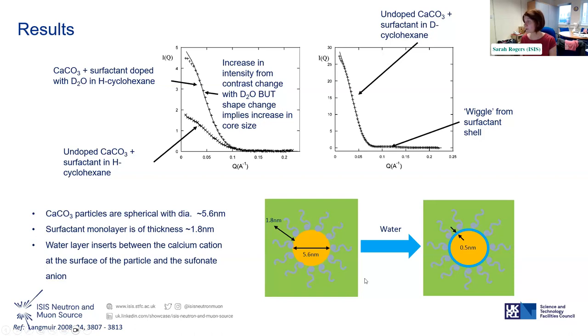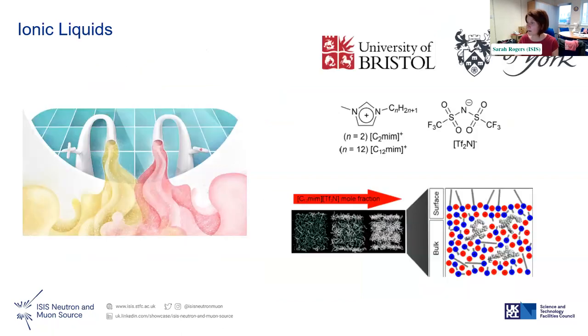And then when we added the water, it does indeed form this very thin layer in between the particle itself and the surfactants. And the more water you add, the bigger that layer gets, the particles break down. That's why they were becoming unstable. So that was a really insightful piece of work.